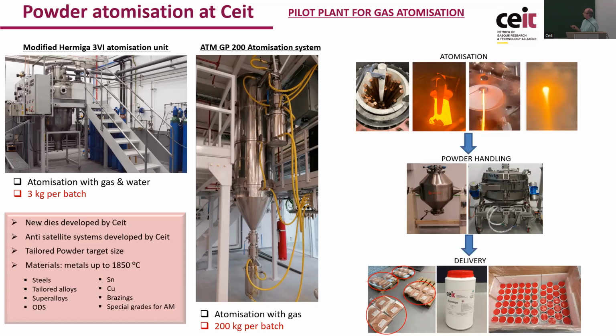When the metal arrives at the atomization chamber, we turn on a supersonic gas flow, we impinge with this metal flow and break into particles. In that way is how we produce the powder. Later, the powder can be mixed with other additives, so we have mixers, or can be sieved to separate the size fraction of interest, like for example in this project. And finally, the powder is packed to transfer to further processing.